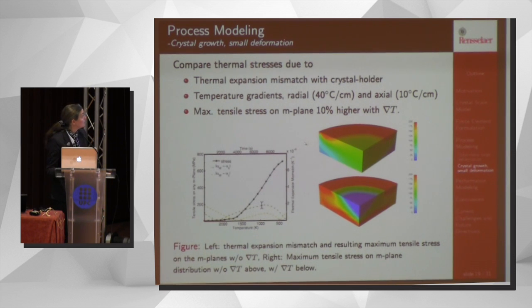And overlaid is the tensile stress on the M plane. So we can see that it starts to grow a lot when we get a higher thermal expansion mismatch. Even though it seems fairly low, it has a very big impact. And actually, the people I was working with at Crystal IS, they did not think that that was going to be important, but it turned out to be the most important thing.